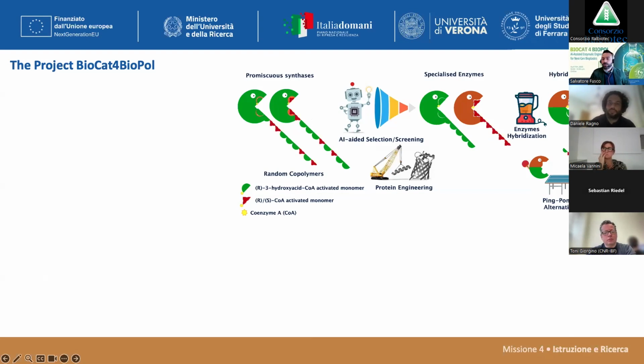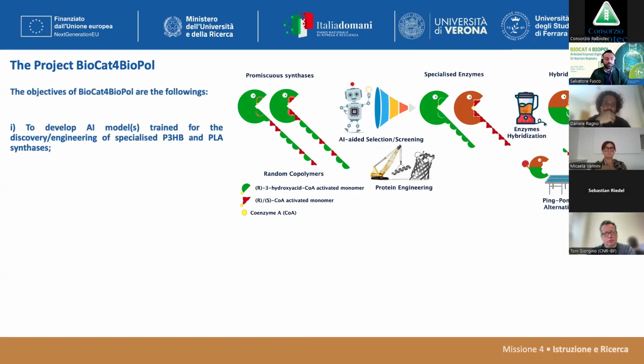What we would like to achieve is an alternating copolymer, because what has been reported is that this kind of copolymer gets degraded at the hydroxyalkanoate area, but the region with PLA is more recalcitrant to degradation. So the objective was to develop a model trained for the discovery and engineering of specialized P3HB and PLA synthase enzymes. We will also tell you that we had issues doing this, because while many people are working with AI, most people are not working in characterizing enzymes, and we need information to feed models. If very little sequence data is characterized out there, you cannot build an AI model, but we found a way to tackle this issue.